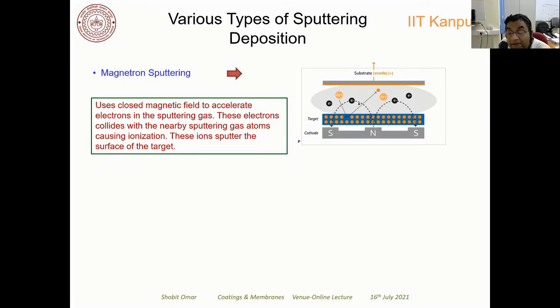Okay? Now, once the electrons are in the cylindrical path, they collide more with the argon atoms, and this results in more ionization of the argon atoms to form these highly energetic argon ions, right? These argon ions are positive in nature. They will try to strike the target material which is negative, basically cathodic, right? So these argon ions strike the cathodic material, and the atoms get ejected out and then reach the substrate. Now, in this case, the distance between the substrate and target is small, compared to what you have in thermal vapor deposition, right? So the chamber is also very small in the case of magnetron sputtering or any type of sputtering technique.